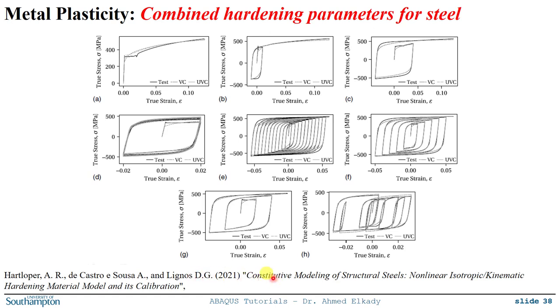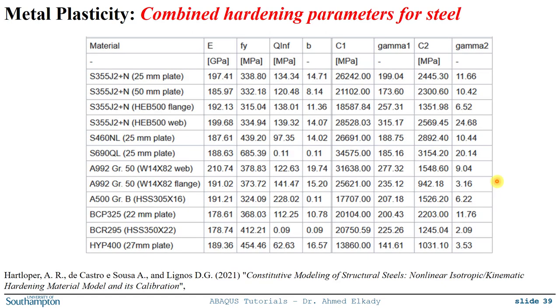So in this reference that I'm showing over here, I put additional references in the video description as well. For steel, you can actually find thorough calibrations that have been conducted for different types of steel materials used in structures, like S355 that's used in Europe, A992 that's used in the US, as well as some other grades that are used in China and so on. So you can use this directly to obtain the values for Q infinity, B, C1 and gamma, and additionally if you want to use two back stresses you can add additional parameters. To obtain those parameters, there is one way, which is doing coupon tests and doing calibration in order to find them, or you can use some available calibration that has already been conducted in the literature.